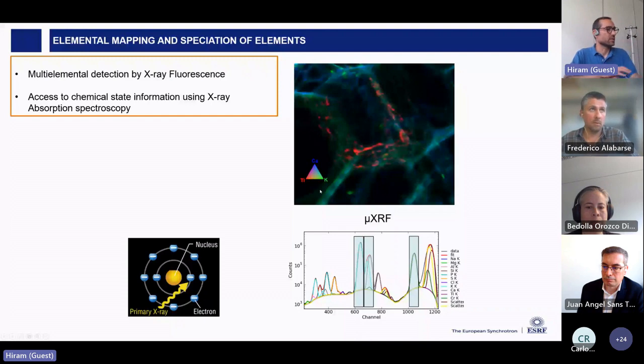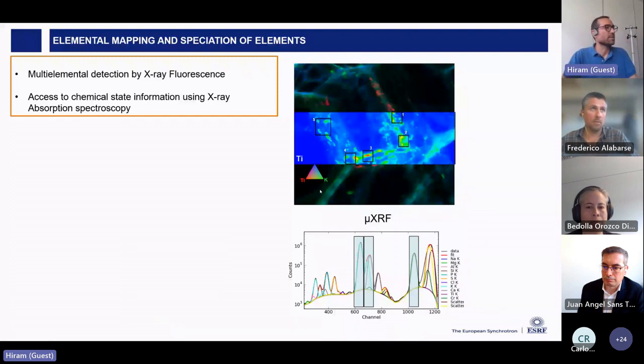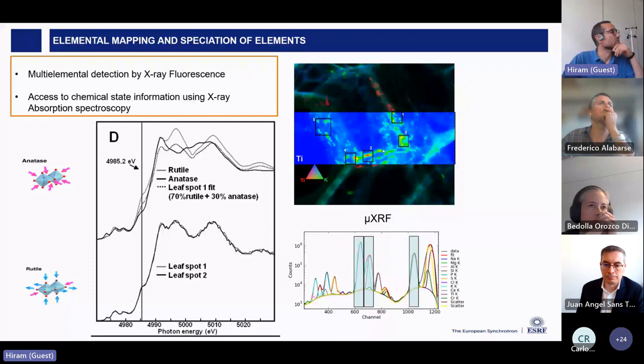And then after, we normally select one element as a target for performing X-ray absorption spectroscopy, and then we can position the beam in the small spots and collect an X-ray absorption spectrum. And by looking at the features of the spectra, we can determine the coordination environment, mainly oxidation state and the kind of neighbors of the atom which is doing the main absorption.